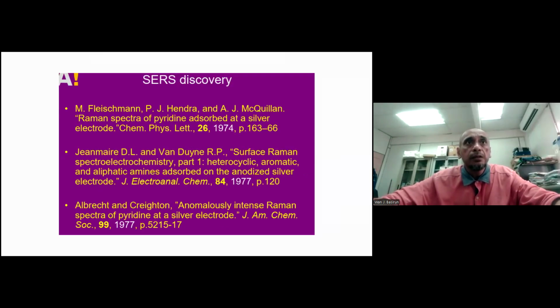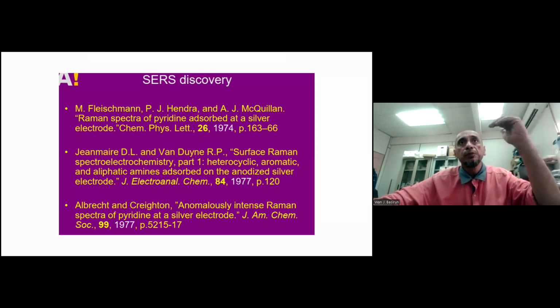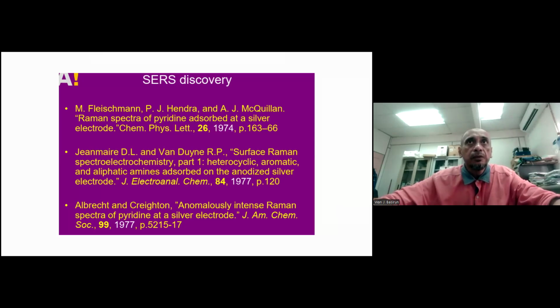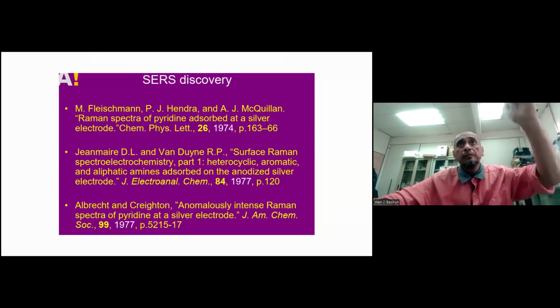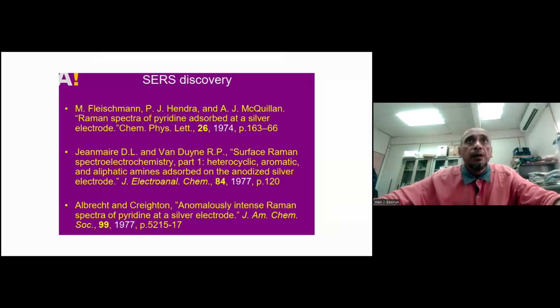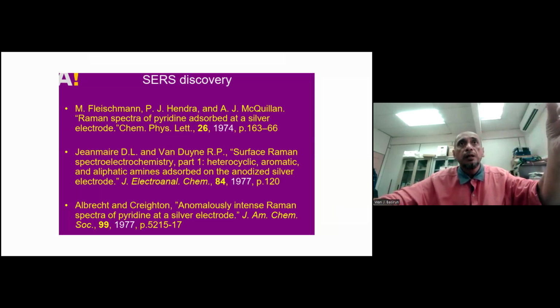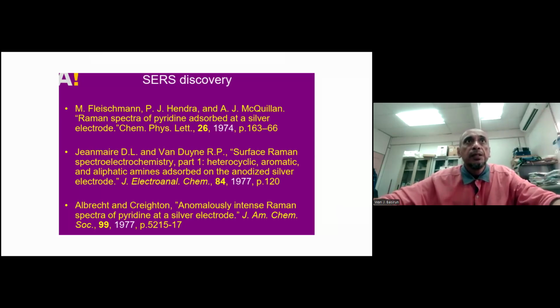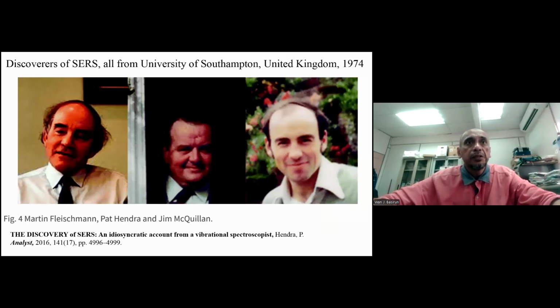Okay, so the SERS discovery was made during the 1970s, when three people observed that when they adsorbed pyridine onto a silver electrode, the intensity became very, very high compared to pyridine on a non-silver electrode. So these are the first people who discovered this effect, and this was at Southampton University. It was reported in 1974.